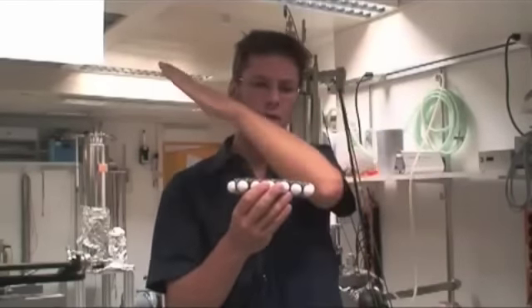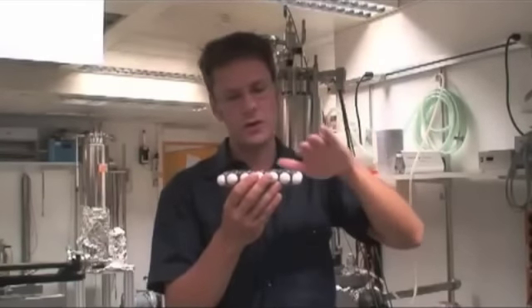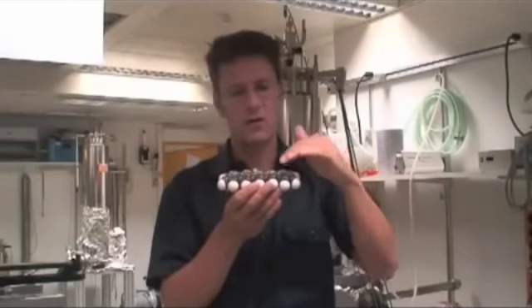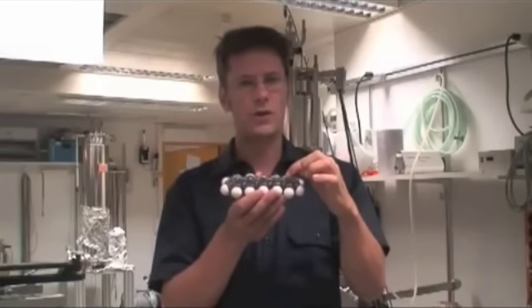So we have this large attractive force that also gives us the dark halo surrounding the molecule. And on top we then get this tiny corrugation which tells us the atomic positions and also the bonds between the carbon and hydrogen atoms.